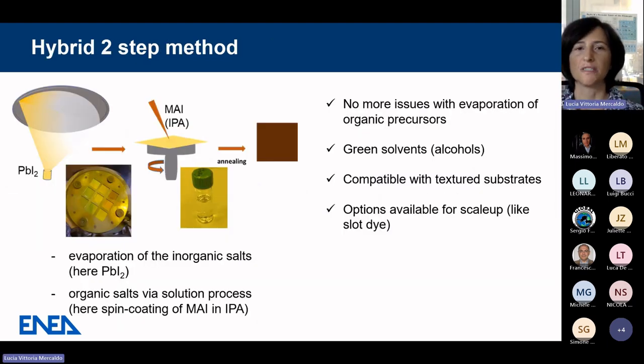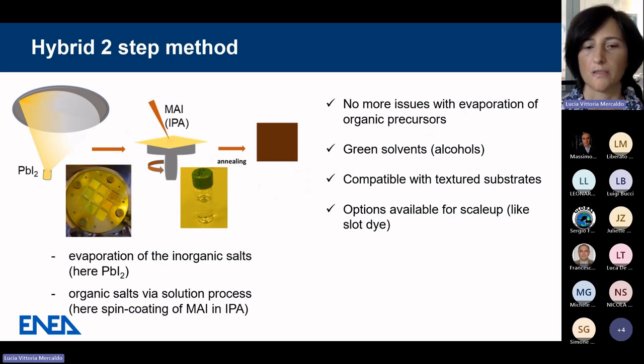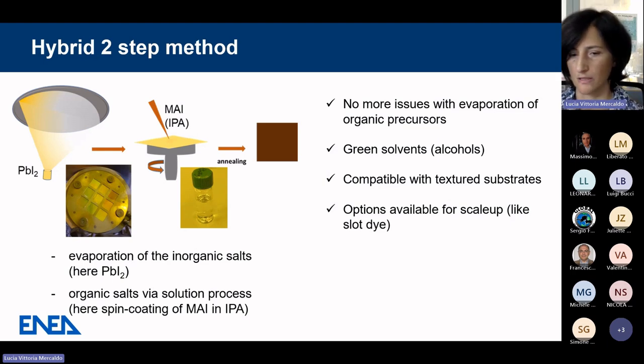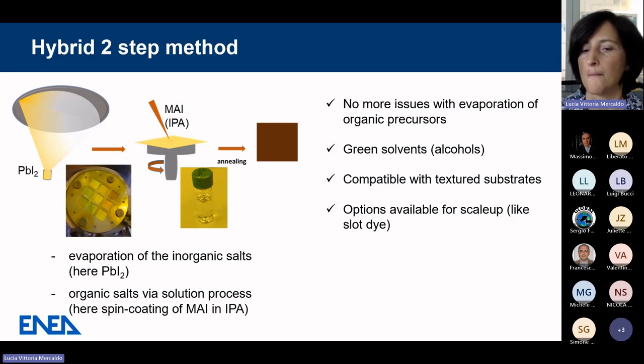Now moving to the hybrid two-step method. What is this method? Here we prepare a template of just inorganic component. So we evaporate the inorganic salts, in this case lead iodide, in the deposition systems that I showed before. And then we move out of the deposition systems, and by spin coating, we apply the organic salts via a solution process. So in our case, spin coating of methyl ammonium iodide in alcohols.